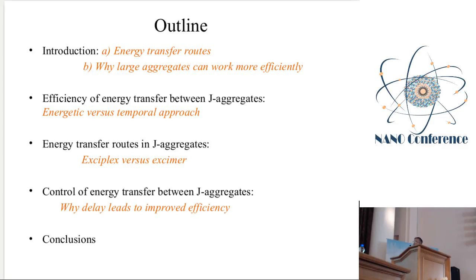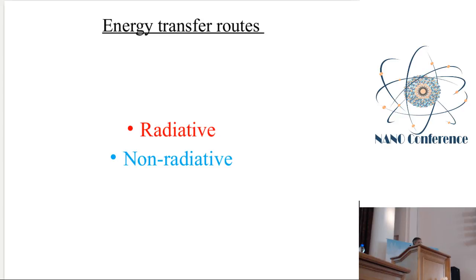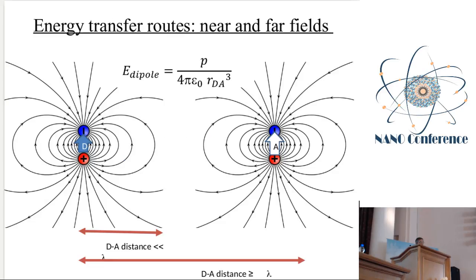So it is well known that energy transfer can take place mainly by two mechanisms, radiative and non-radiative. The main difference between these mechanisms is the distance between a donor of energy and an acceptor of energy. For example, if we have a relatively large distance between donor and acceptor, which is higher than the wavelength which the donor emits, then we have the so-called far-field case, when energy can be transferred only in a radiative way. And if we have a relatively small distance between donor and acceptor of energy, we can transfer energy in a non-radiative way.